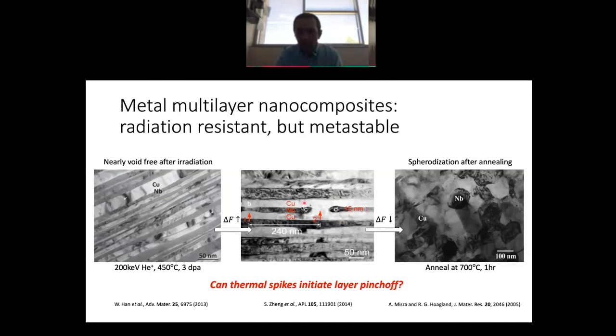And this pinch off that you see here is actually the first step in the process of the breakdown of the microstructure. And so the question is, if I have this multilayer under irradiation and it's subjected to these high energy thermal spikes with extremely high temperatures, can the thermal spikes initiate layer pinch off? Okay, so in other words, can thermal spikes destabilize the microstructure of these materials?